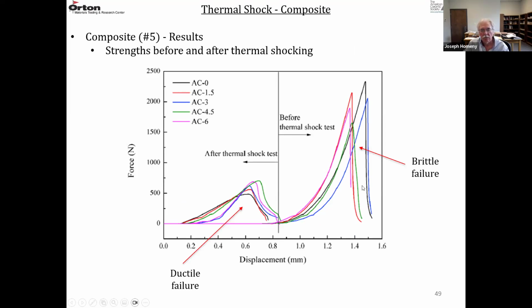And the right-hand side is before thermal shocking. So it's pretty linear up until failure with a rapid drop in strength. That's a brittle fracture. But the materials after thermal shock, they were non-linear and stable type fractures after the crack started to propagate. So these are more ductile or less brittle after thermal shocking.